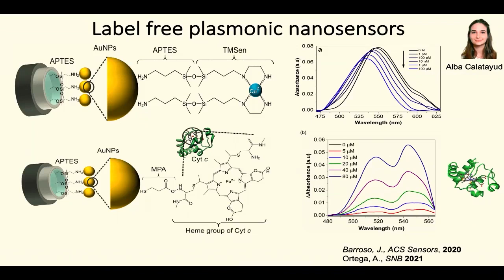And I think this is interesting because we have a very clear peak of the cytochrome C. And people ask me, how is it possible that you get that if there are so many other proteins in plasma? And this is correct, but most probably only the cytochrome C is the one whose UV-Vis spectrum overlaps with the scattering spectra of the gold nanoparticles. So if we open the range of the gold nanoparticle spectra, we will be able to see more proteins. More proteins interact with the particles, but we only see the cytochrome C.